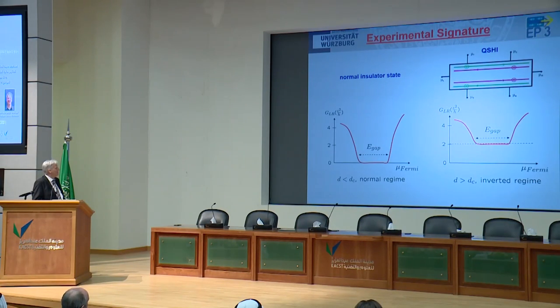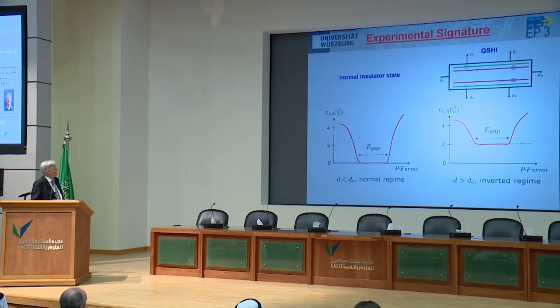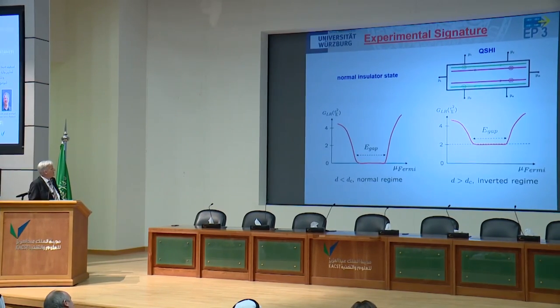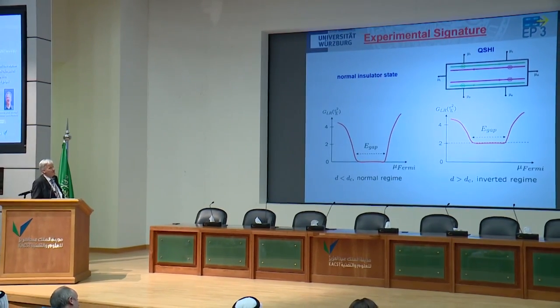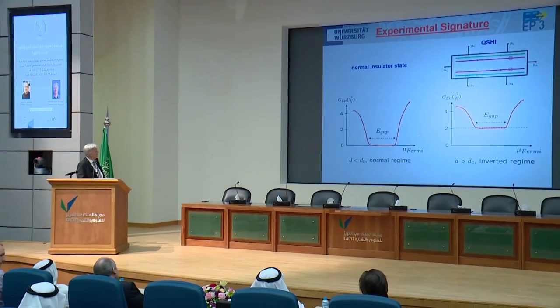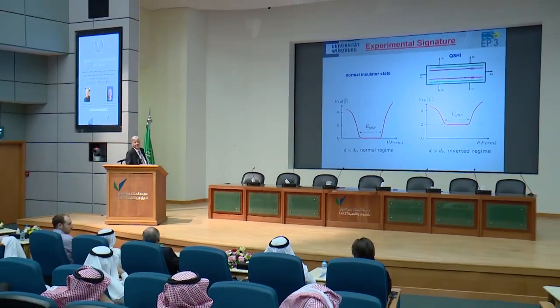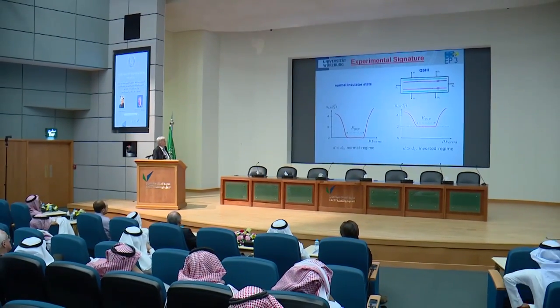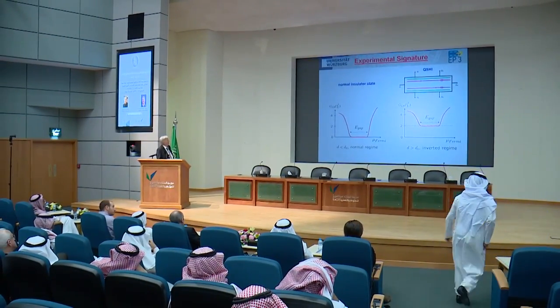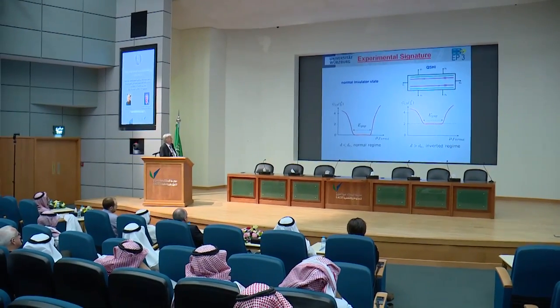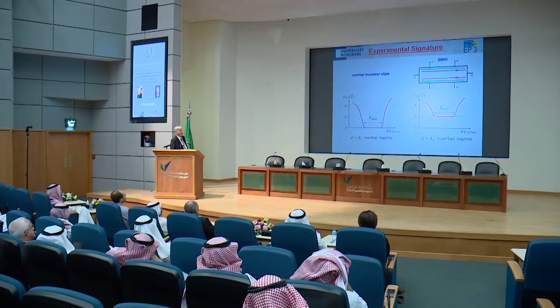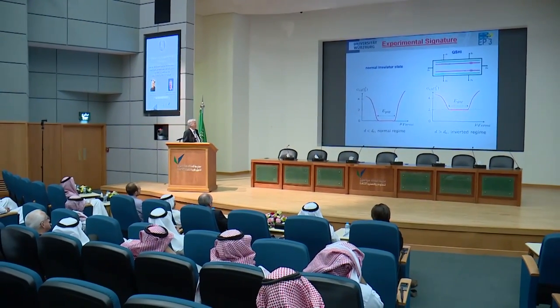Now, a first very simple experiment to look at this is shown here. This is the conductance measurement on a Hall bar, so it has these six probes here. You bias, you push a current from here, you ground here, and you look at longitudinal conductance. Now, if you have your normal insulator, these edge channels are not there when the Fermi level is in the bulk. So if you scan your Fermi level through the gap, of course, the conductance is zero in the gap. But if I have now this inverted material with edge channel conductance, I have one spin-up channel going from left to right and one spin-down channel going from left to right. That means that my conductance is quantized in 2e squared over h. And that's where the whole thing started.